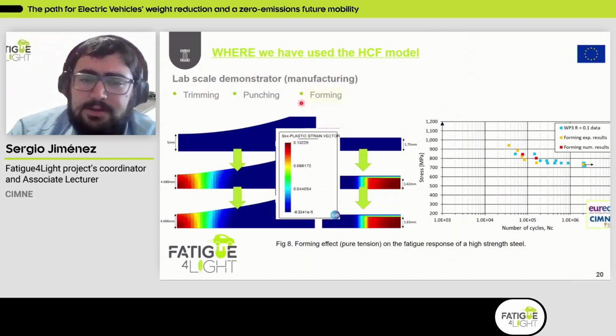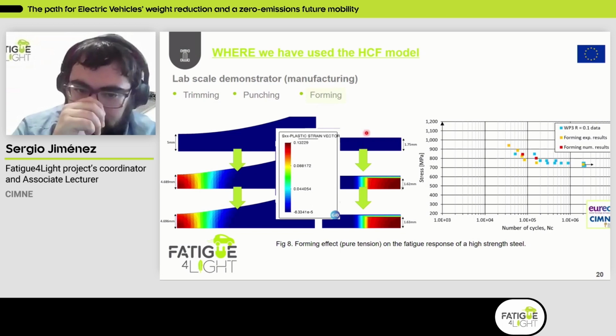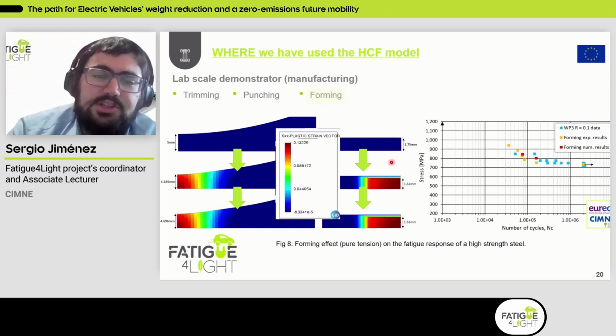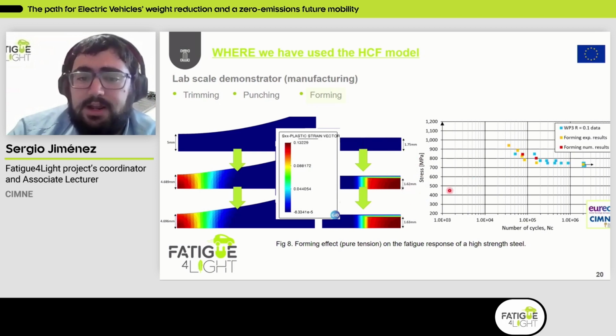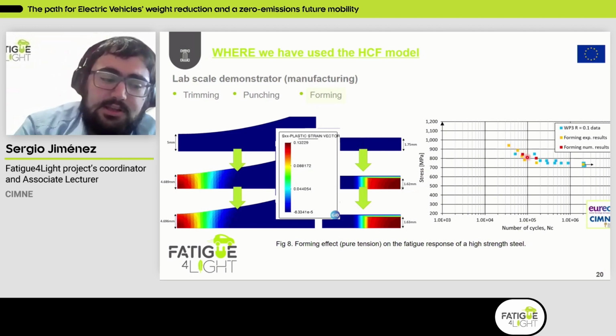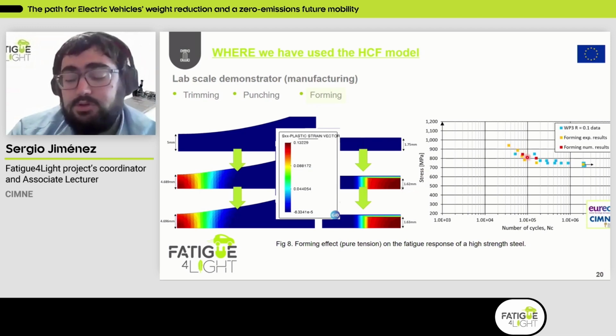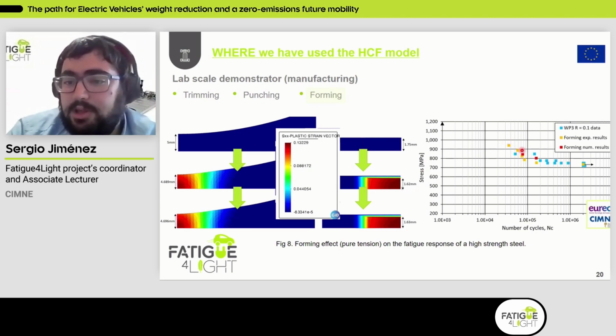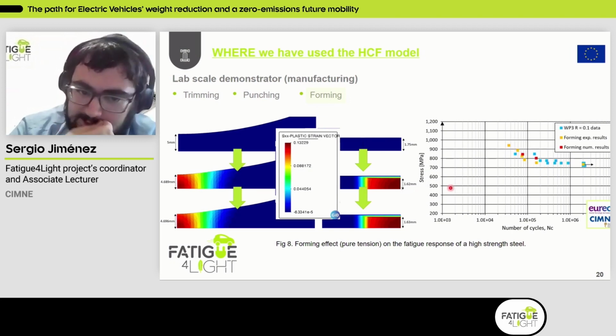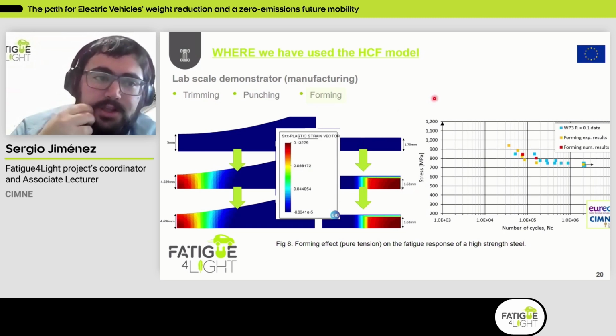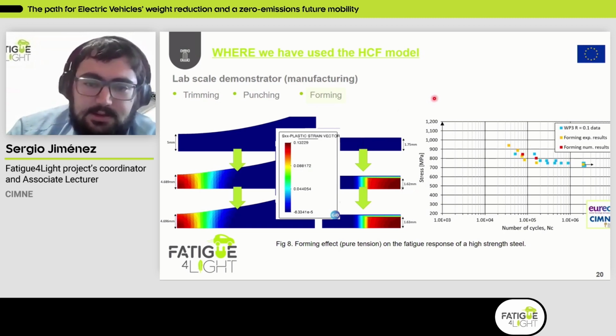And then with respect to forming, basically what we've done here for this particular scenario is applying a tensile load, which induces some plastic strains on the material. And then for this sample, we applied a cyclic load up to the failure. And this is the approach that is being followed experimentally, and we reproduce that from a numerical point of view, and we're obtaining nearly the same results experimentally and numerically. So good news, because the model is able to capture this type of effects affecting fatigue.